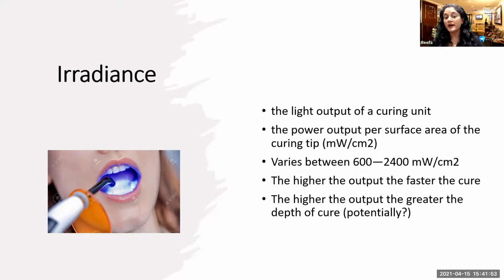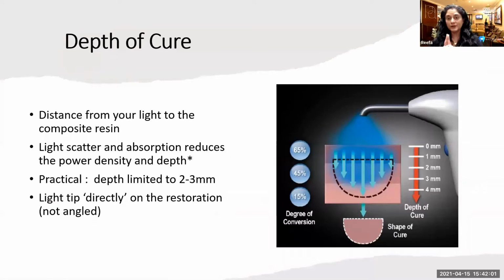Now, the higher the output, the greater the depth of cure they think, but they're not quite sure about this as yet. Depth of cure is a very important thing, and we're going to talk a little bit about that. Essentially, you're looking at the distance from your light to the composite resin. Light scatter and absorption reduce the power density and the depth. If you look right down the center of this, the degree of conversion at the base, down 4 millimeters, is only about 15%.